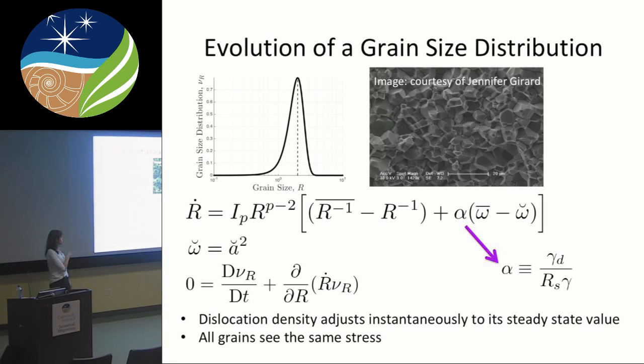Something that pops out from the ensemble model: to go through it, we had to look at more robust thermodynamic processes. So we're tracking the evolution of energy and entropy within the entire system. And something that pops out is that this alpha really stands for the competition between the energy, gamma D, associated with each dislocation, so energy per dislocation length, and the energy of the grain boundary. So it's more like a surface energy. So alpha, which is somewhat intuitive, the amount to which dislocation density contributes to grain growth, is really the competition of the energy contribution from dislocations, gamma D, and the energy associated with the surface.